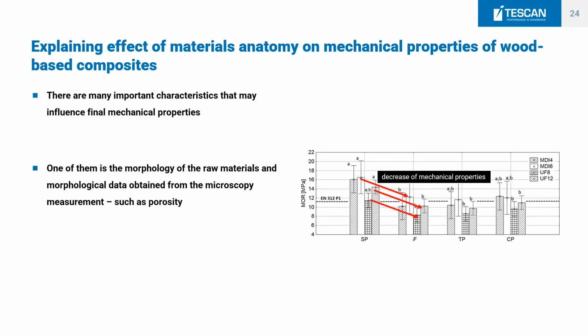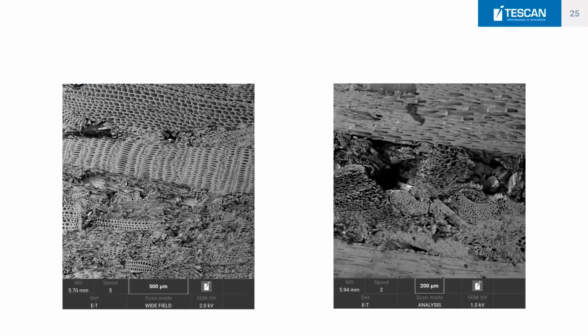Of course, there are many important characteristics that may influence final mechanical properties, but one of them is the morphology aspect. That is how the raw materials differ compared to wood, and what data I can obtain from the image, such as porosity or the adhesive penetration. On the left-hand side and right-hand side, there are two SEM images. On the left-hand side, you can see that the image is totally different than on the right-hand side. You don't need to be a genius to tell that the right-hand side is a completely different material. You can see that there are bigger pores, that the cell walls might be different, and that it consists of more features, right?